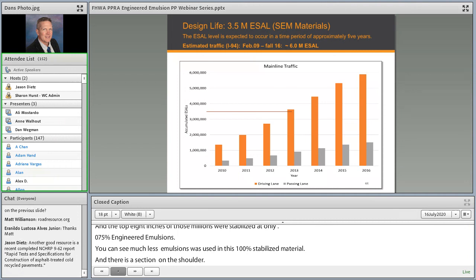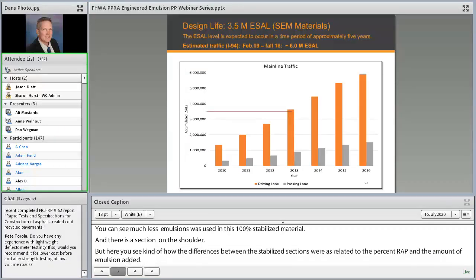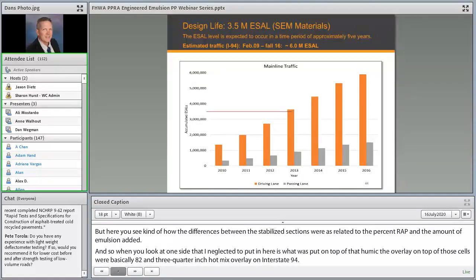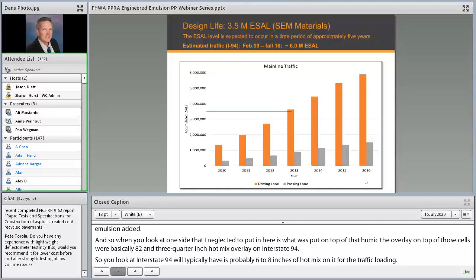And so when you look at one slide that I neglected to put in here is what was put on top of that. The overlay on top of those cells was basically a 2 3/4 inch hot mix overlay on Interstate 94. You look at what an Interstate 94 typically would probably have, 6 to 8 inches of hot mix on it for the traffic loading. Here they're only putting 2 3/4 to 3 inches of hot mix on top.